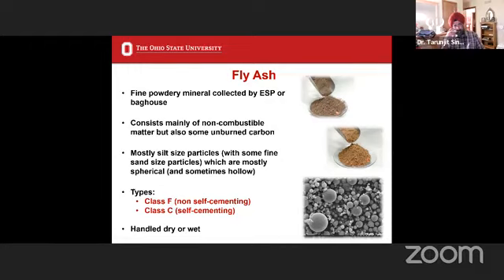In literature, because class F fly ash has the particle size distribution of silt, it was assumed that when you wet it, it will have cohesion. And this is something that we have worked on, a contribution that my research team has made over the last 20 years: while class F fly ash has the particle size distribution of silt, in fact, the silt we are talking about here is a coarse silt. Now keep in mind that the line between silt and sand is an interface, right? Although we have numbers saying below and above, what we have in real life is that while fly ash particles technically are coarse silt, they are so close to fine sand that they actually behave like non-cohesive materials.